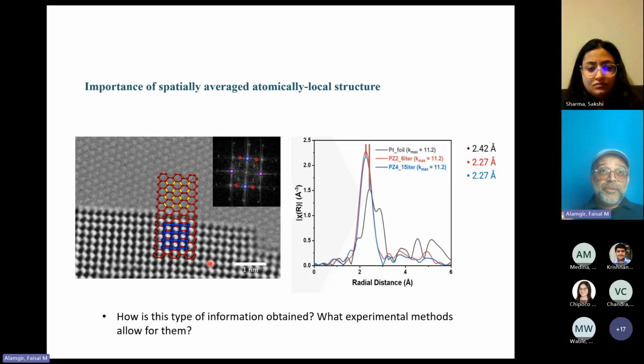However, if you really want to be sure about what's happening in a global way, what you want is a method to get local atomic structure, but averaged over many microns or millimeters of your material at the same time. So in other words, you would want to use a method which is designed to be spatially averaged at the macro scale. However, that same method gives you information that is extremely local, that is atomic scale. So atomic scale information, but spatially averaged over macroscopic scale.